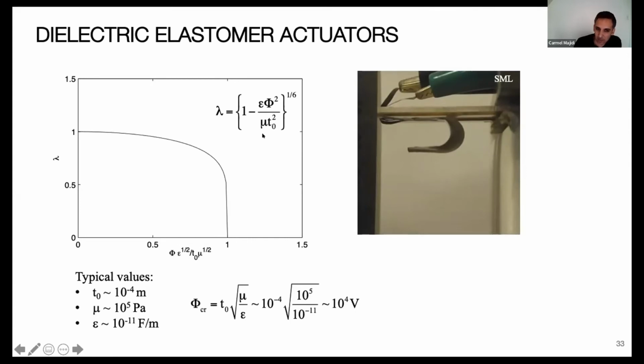Now, another outcome of this is that we see this instability within dielectric elastomer actuators. This is something anticipated by our thermodynamic formulation, and it's also something that we see experimentally as well, right? And so, here's a case of a dielectric elastomer actuator where at some point you're going to see this electromechanical instability that's going to result in this dielectric breakdown of the material. So you'll see that there's that little spark there in the corner. I'll just play that again, just so you can see that.